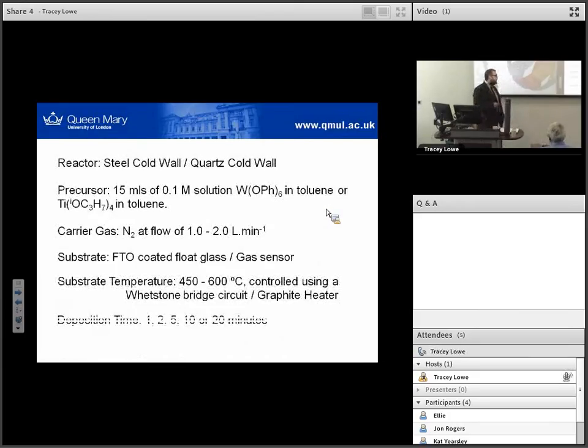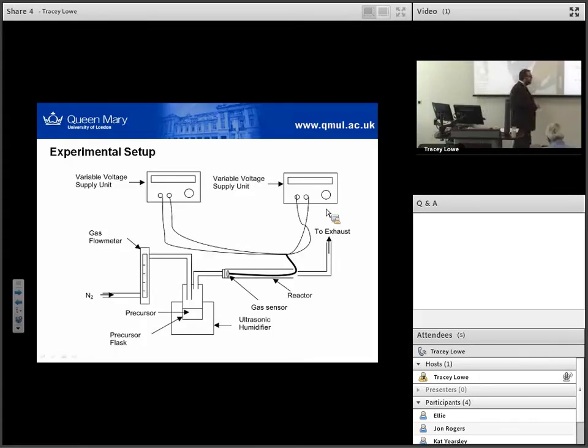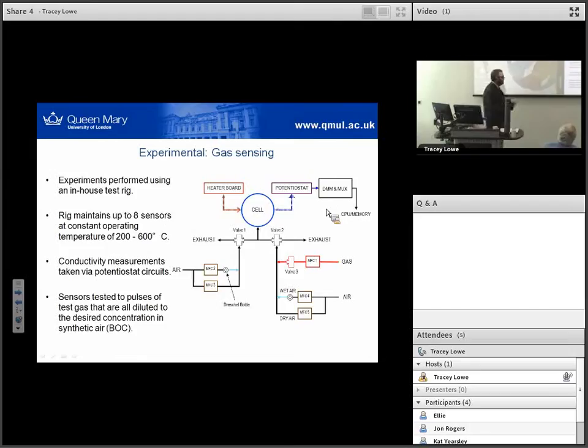In this case, we're going to make some tungsten and titanium oxide sensors, again using these standard conditions, changing our electric field strength. Rather than our traditional cold wall reactor, we put a gas sensor chip with no coating into a metal tube and flow our aerosol across the top. We use the gas sensor's integrated heater to reach deposition temperature, and apply an electric field across those interdigitated electrodes. All of the gas sensing work we do in-house.